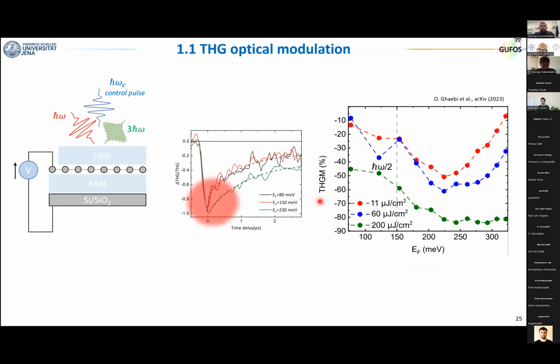There is one final thing, now that we know that we can have this tunability. So now I told you that in graphene, we can control the third harmonic electrically, and we can change the modulation. We can control the dynamics because we can make it slower or faster depending on the value of the Fermi energy. And we can also control the total amplitude in an all-optical fashion. Because now you see that the third harmonic modulation, so if you take the maximum of these dynamics, here it's all normalized, but here you see it in percentage, then if you increase the pump fluence or the fluence of the control pulse, of course you change the maximum modulation depth, but the maximum modulation depth is also a function of the doping or the Fermi energy.